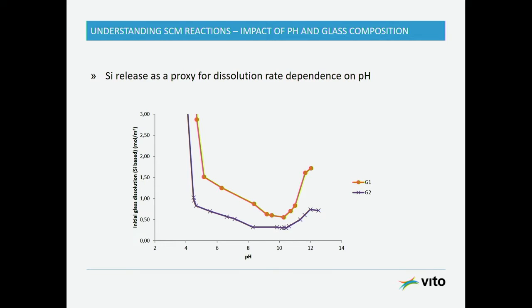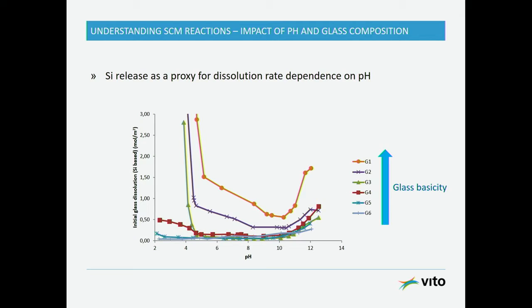So also there we see this clear dependence on the composition of the solution, of the glasses. So we see here that when we move to more aluminosilicate-rich glasses, we really slow down the dissolution rates, and we get a very broad pH range where we get the stability of the glass. So for these glasses, you really need higher pH to be able to make them dissolve or react at the longer term. And this is what you can see also for the other glasses here. So these are very silica-rich glasses. They really become only soluble here at the higher pH range.